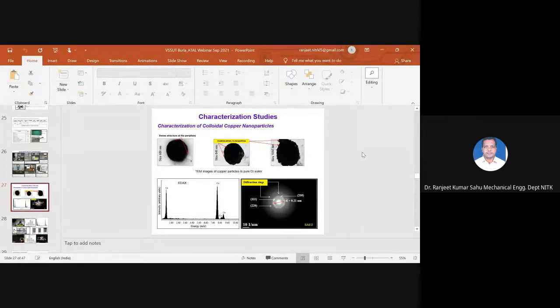See, when the copper particles, the debris which are produced in the dielectric fluid, we have taken for the TEM study, we found that very large size copper particles are produced in the range of 680 nanometer up to 1050 nanometer. Okay, that large size copper particles are particularly caused due to the agglomeration of the particles. That means the particles are agglomerating, they are becoming very large size particles. And this agglomeration occurs due to the combination of van der Waals forces of attraction and Brownian motion, which occurred during condensation and nucleation of the copper metallic vapors. So these are the large size copper particles we found.